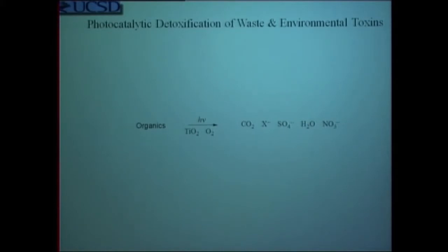So once again, this kind of interaction allows you to take a variety of organics and in a non-aqueous solvent in the presence of oxygen, convert virtually all the carbon atoms ultimately to their elemental state. So that means virtually any substituted organic material will go to carbon dioxide, halide, sulfide, water, or a nitrogen oxide. This is important because it represents a way of doing cleanup. There was a U.S. patent issued about 7 years ago to Adam Heller and his co-workers at the University of Texas in which this was suggested as a way to clean up oil spills. In other words, you take tons of titanium dioxide and spread it over an oil spill and let the material be converted to CO2 rather than to a pollutant spoiling the beaches.